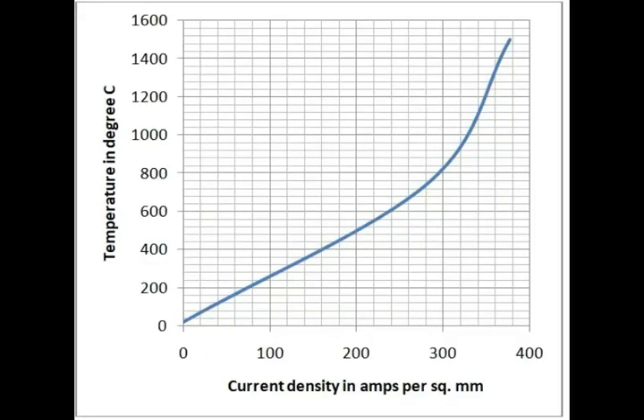This is a plot of current density versus temperature. At 300 amperes per square millimeter the temperature is about 820 degrees Celsius, and at 330 amperes per square millimeter, the temperature is about 1000 degrees Celsius. If you can keep on welding between these two current densities, you can eliminate all expulsions.